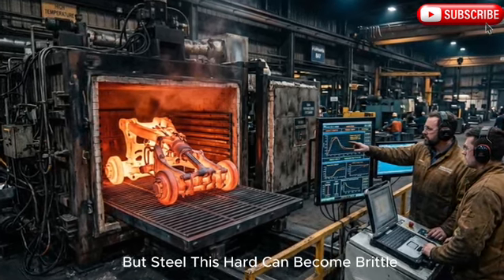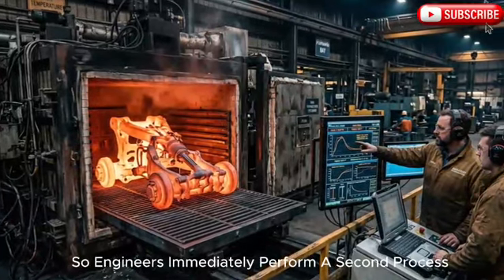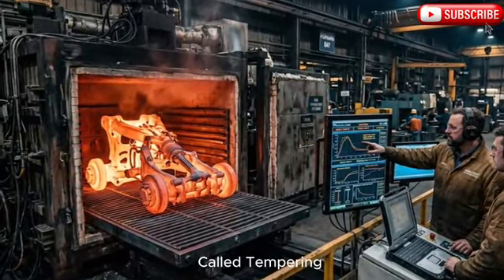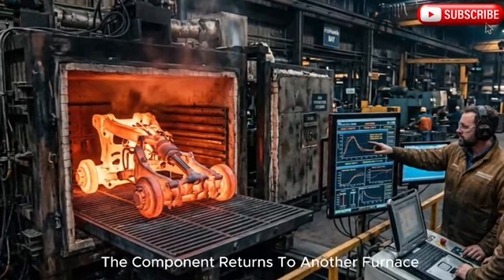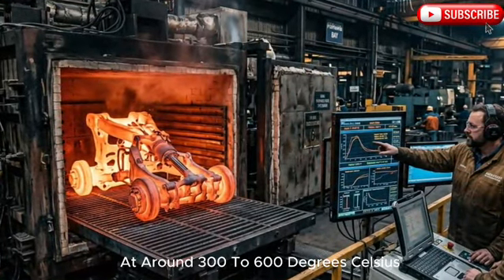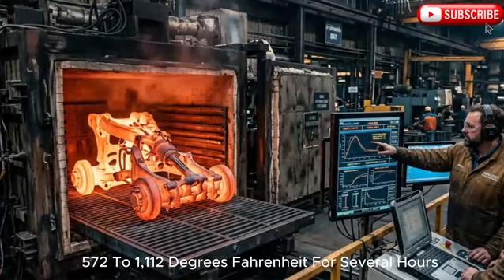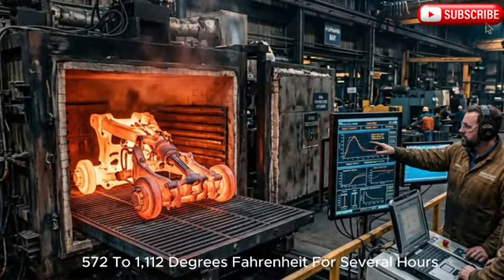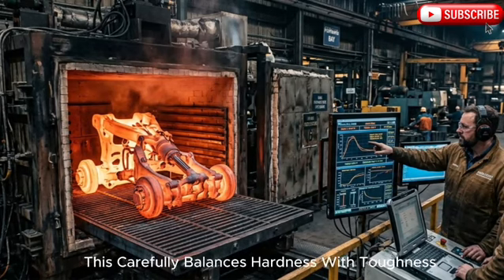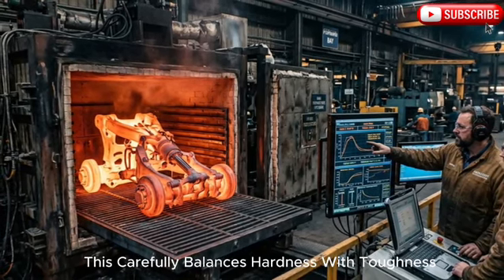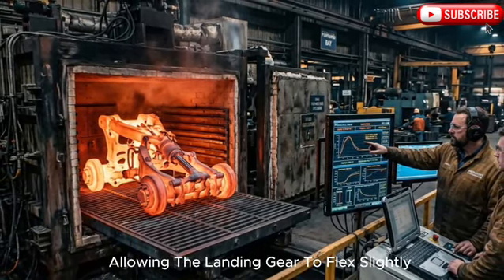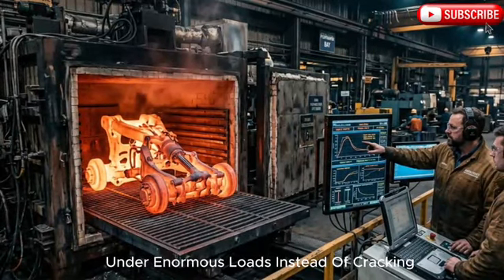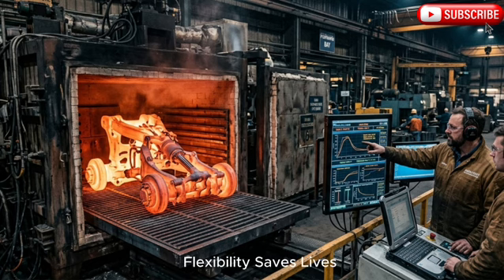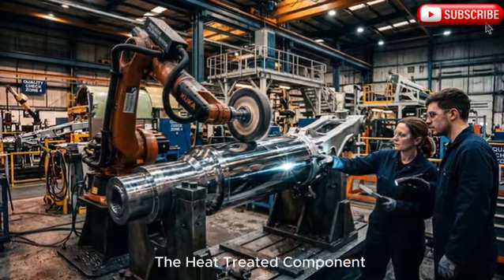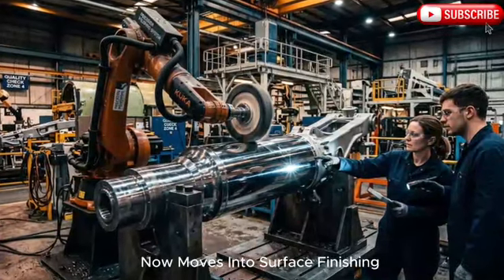But steel this hard can become brittle, so engineers immediately perform a second process called tempering. The component returns to another furnace at around 300 to 600 degrees Celsius, 572 to 1,112 degrees Fahrenheit, for several hours. This carefully balances hardness with toughness, allowing the landing gear to flex slightly under enormous loads instead of cracking. Most people never realize that strength alone isn't enough. Controlled flexibility saves lives. The heat-treated component now moves into surface finishing.